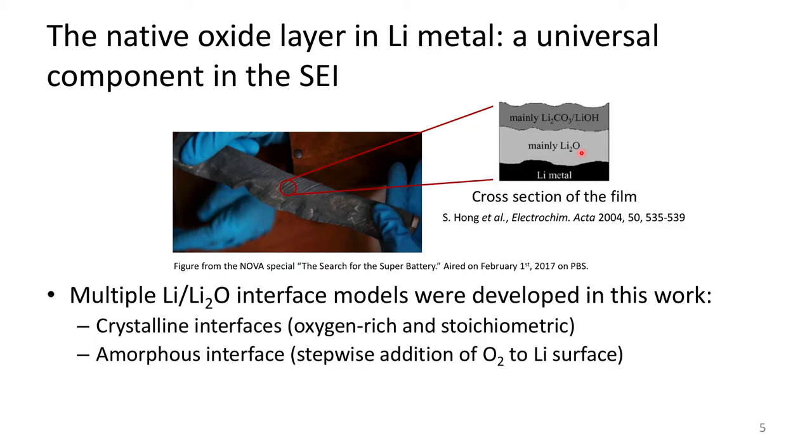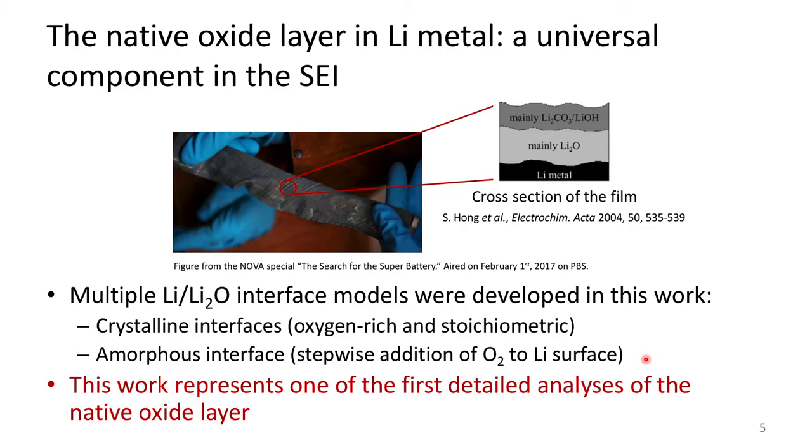To do so, I considered multiple interface models: 2 crystalline interfaces with differing terminations of the lithium oxide layer, resulting in stoichiometric and oxygen-rich compositions, and an amorphous interface which was grown through the stepwise addition of oxygen molecules to a lithium surface. While the crystalline interface is what's typically created to study these types of systems with DFT, I felt it was important to also create an amorphous interface that more closely mimics the process by which the native oxide layer forms in nature. And to my knowledge, this is one of the first detailed analyses of the native oxide layer.